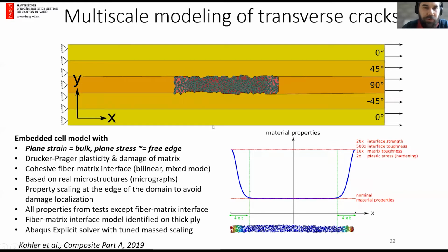Thin-Ply in a multiscale manner by discretizing the microstructure of a transverse ply here, with each fiber modeled from a micrograph, with cohesive interfaces between the fibers and the matrix. The matrix itself is a Drucker-Prager plasticity model with damage. And the neighboring plies are modeled as continuum elements here to model the constraining effects of the neighbors.